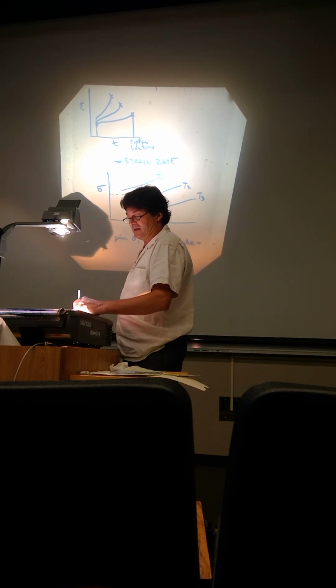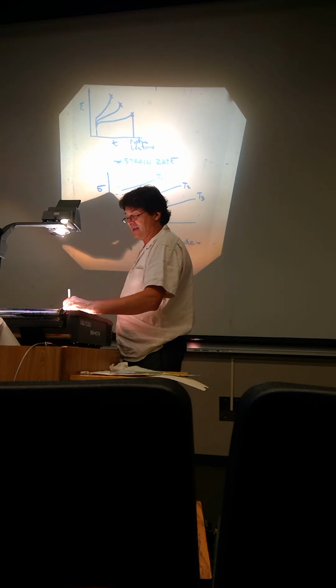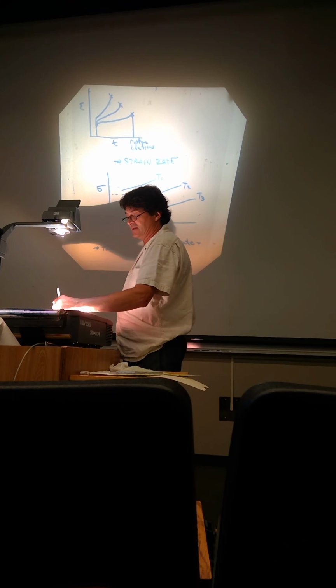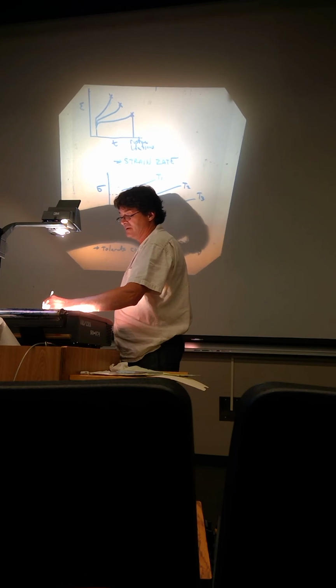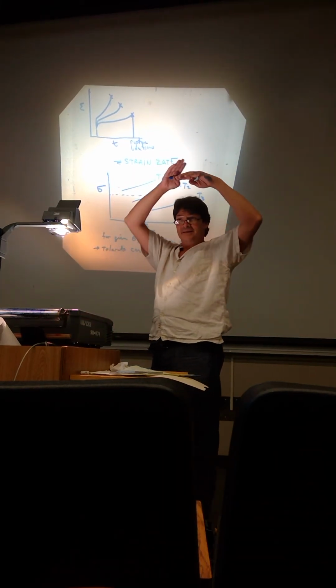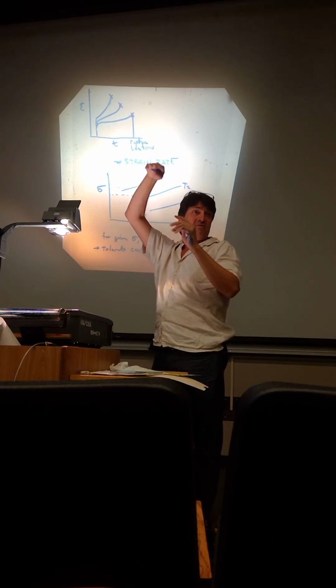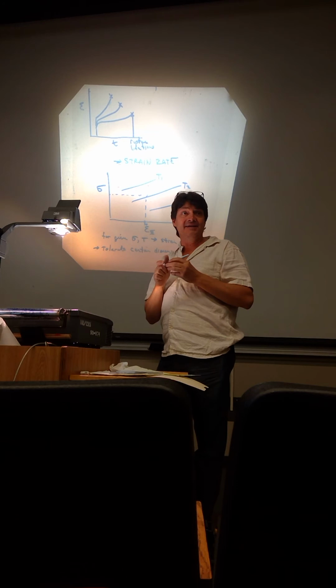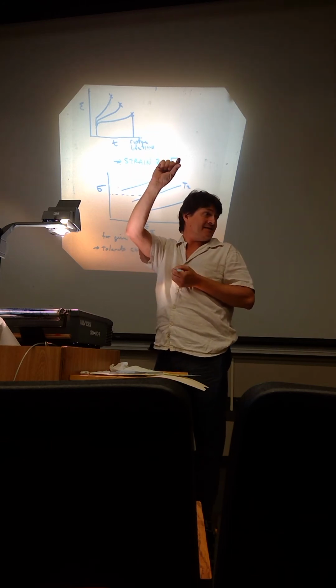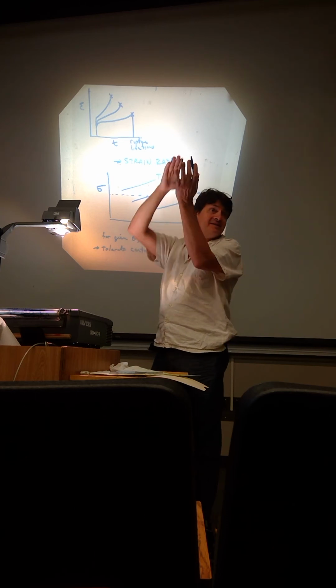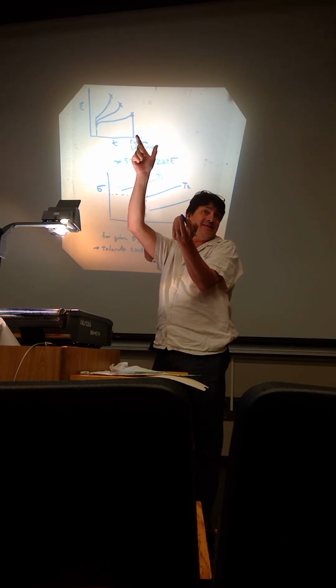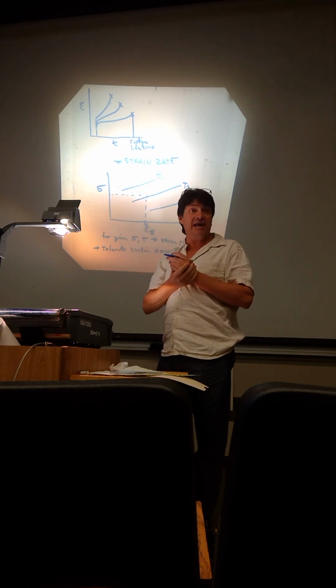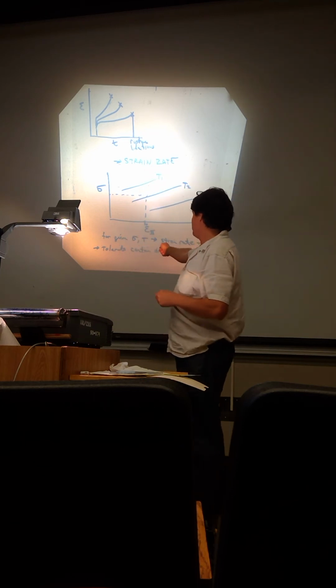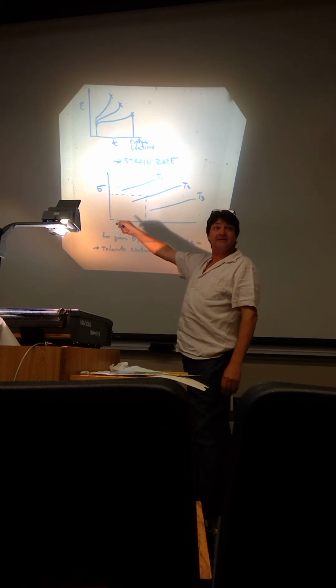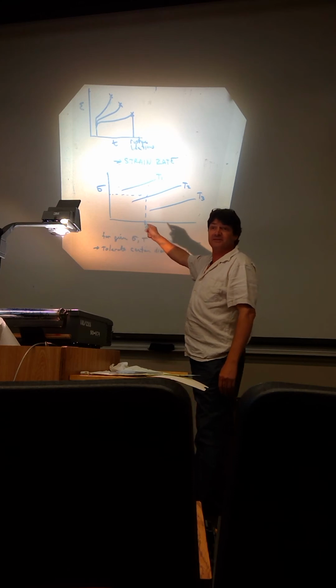Then you know you can tolerate a certain dimensional change. Say your turbine blade can get 1/10 of an inch longer before it hits the rotor. You can calculate that dimensional change. What's the strain you can tolerate? It's a 1-inch blade. It can grow 1/10 of an inch. You can have 10% strain before it's going to hit something. You know your strain rate. You now can calculate how long it'll take to get 10% strain.